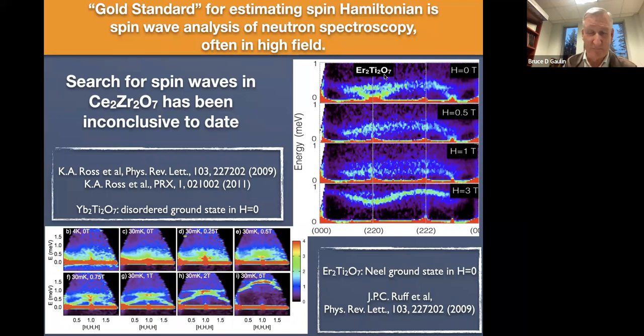And here are results from erbium titanate, which actually orders in zero field. So you see nice spin waves even in zero field, but then you can destroy that order and go into a spin polarized state at high fields. You can fit these spin waves either in zero field or high field or both, and you can get good estimates for the microscopic Hamiltonian parameters by doing that. And you can do the same thing, and this is just another example from ytterbium titanate. So that's what we would do if we could.